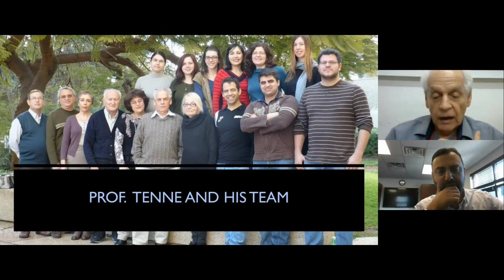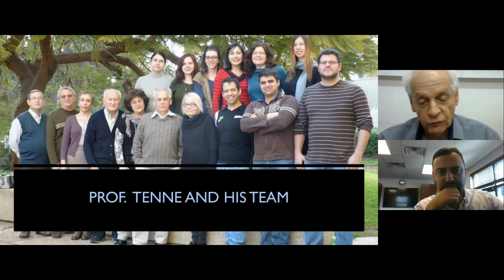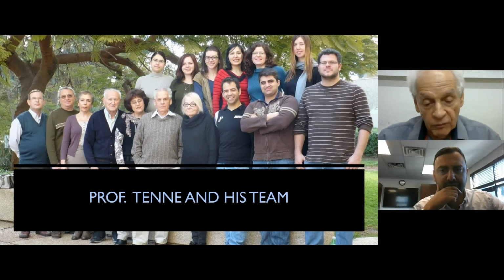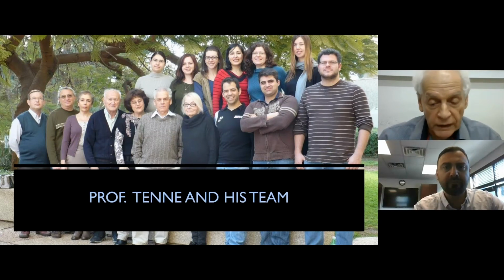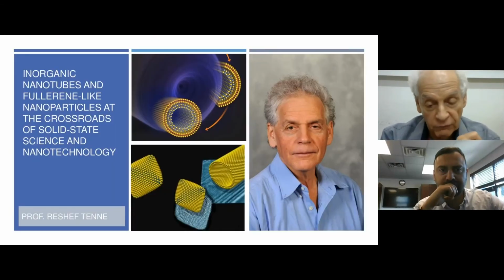Now think about a large scale application when you have a pot of 1 ton where you want to mix these nanotubes. Think how much energy you have to dispense in order to mix them evenly in the case of carbon nanotubes or graphene versus these nanotubes. It's unimaginable, the difference. So they disperse very well, and even though in theory they are 5 times weaker than carbon nanotubes, engineering-wise they are only a factor of 2 weaker, not more, because we know how to synthesize them very well, and they are very strong and very robust.